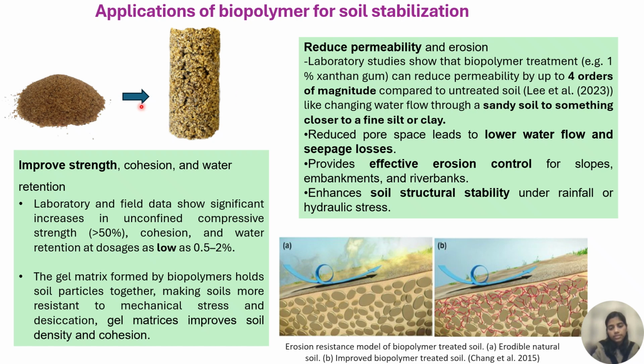This is with a very small dosage of biopolymer treatment, around 0.5 to 2% by weight of dry soil. Even with that small amount, the transformation is very interesting, right? Studies show that this treatment can increase the unconfined compressive strength by over 50% while also improving the cohesion and water retention. The gel matrix formed by the biopolymer binds soil particles together, making the soil much more resistant to mechanical stresses and cracking when it dries out. In other words, it doesn't just get stronger, it also becomes more flexible and resilient.